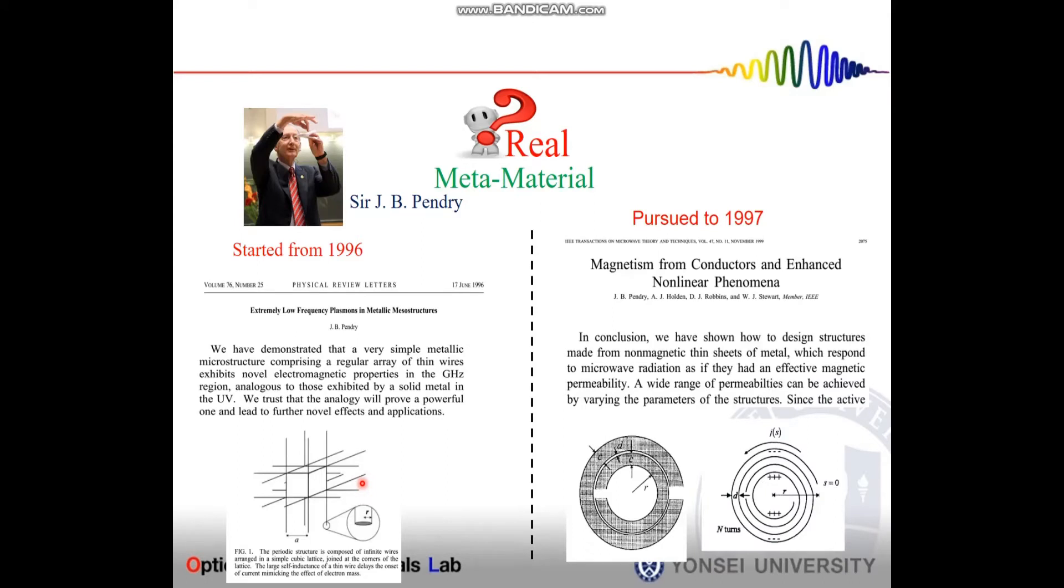And the very next year, he also introduced a capacitive element into the system which is resonant and the negative response can be induced. It is popularly known as the split ring resonator. When electromagnetic waves interact with this split ring resonator, it induces the negative magnetic permeability. Both things are very much sensitive to the physical parameter of the structure.